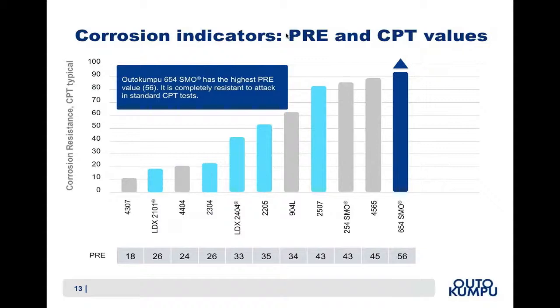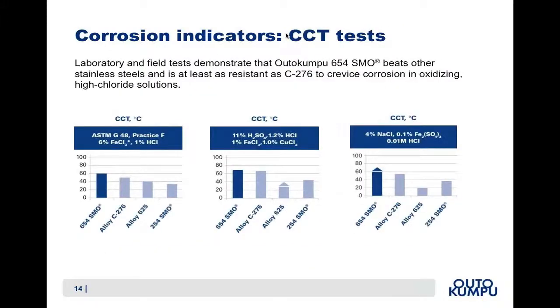So let's turn now to the corrosion indicators of the PRE and CPT values. You can see from this chart that we've plotted 654 SMO against a wide range of other stainless steels, and you can see that 654 SMO offers superior PRE and CPT performance to any other material we supply. We also have other important corrosion indicators such as CCT tests, and again, as these charts show, 654 SMO offers superior performance to other stainless steels as well as the alloy C276.